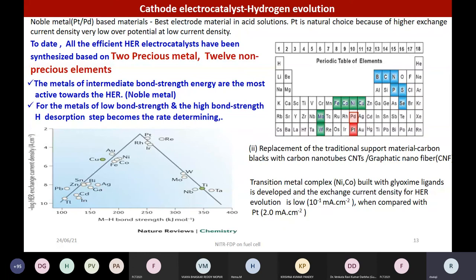But there are a few other catalysts, nickel, cobalt, iron, and copper, also being used as hydrogen evolution reaction catalysts. Though they give on par performance with the noble metal electrocatalyst, the stability of the catalyst over a period of time in acidic medium is a question mark. So that's why, if you want to make a system with a non-noble metal based electrocatalyst, it may not have high stability. It is giving on-par performance with platinum based catalysts, but the durability is the question mark.